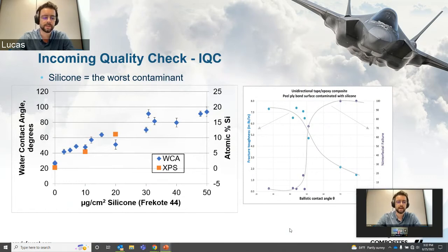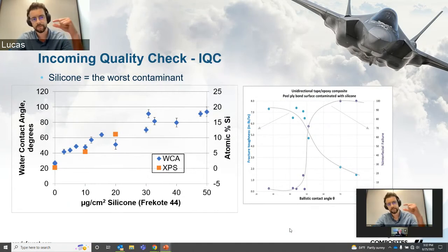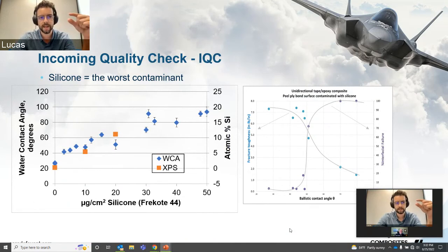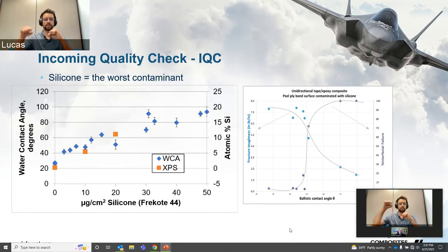Which give us a lot of confidence that if we design our process well to create a particular surface chemistry, part after part, shift after shift, operator after operator, that gives us a very specific water contact angle band that any movement in that band can alert us to when things are moving out of spec. Just like we would put a torque specification on a fastener, we can put a specification on surface chemistry for the factory. On the left-hand chart, we're showing the technique sensitivity to silicone.